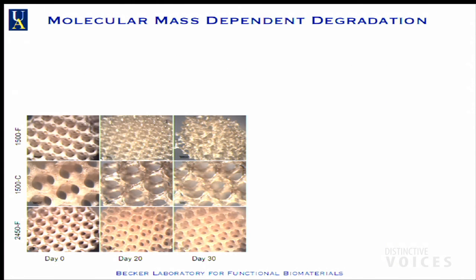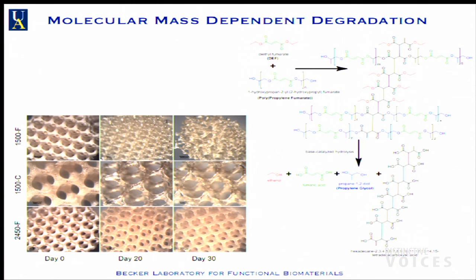Most significantly, this is day 0, day 20, day 30, with, I think, the 1500 fine structure, 1500 coarse, and then the higher molecular weight. There are no defects in the pattern. And so it truly is a surface eroding mechanism. And so you don't get chunks breaking off, which would be counterproductive to your bone healing process.